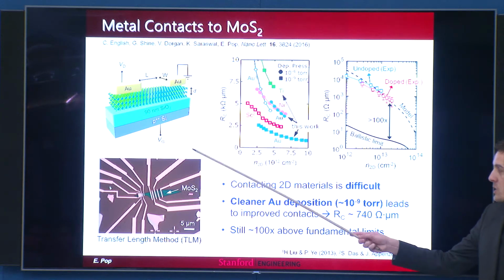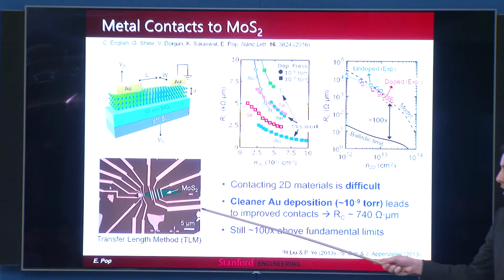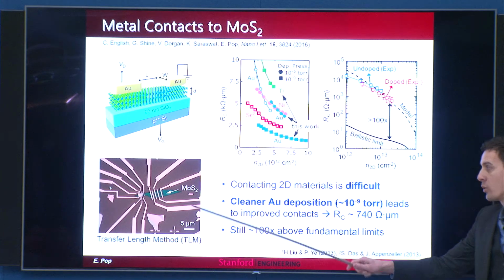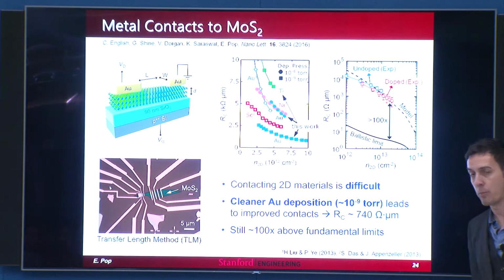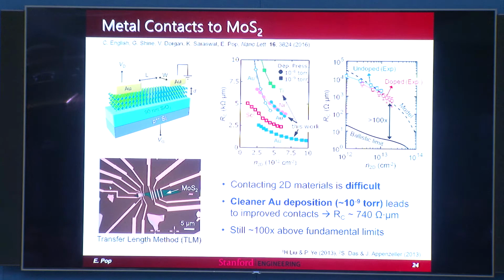If you're worried about sticking, you still use Ti/gold underneath the pads and farther out. But these leads right here are pure gold, and those are actually the best contacts in our group right now. The contact resistance is below a kilohm-micron, but this really ought to be about a factor of 10 lower. These are undoped contacts, so doping of course helps, as I'll show in a moment.